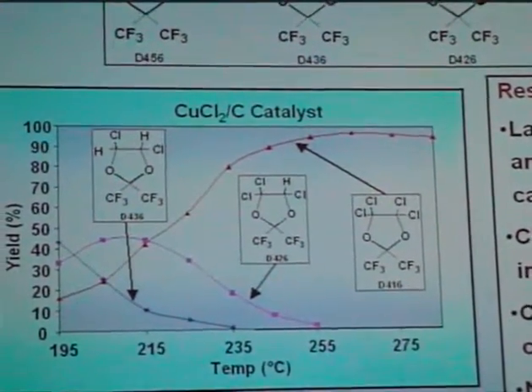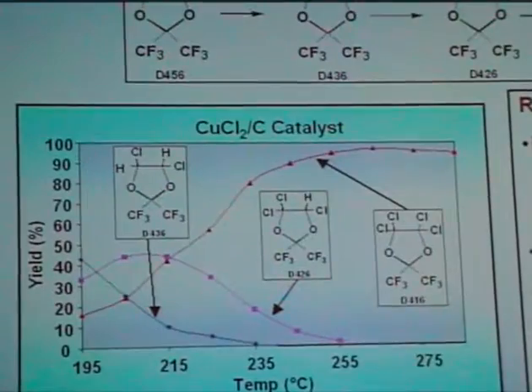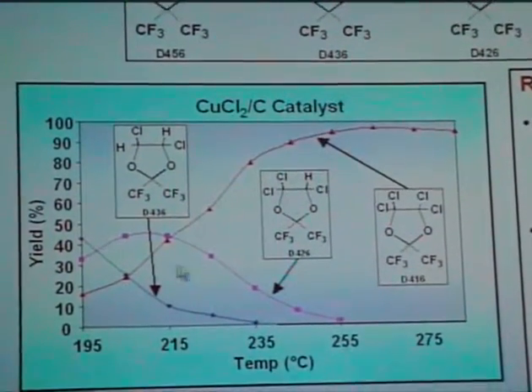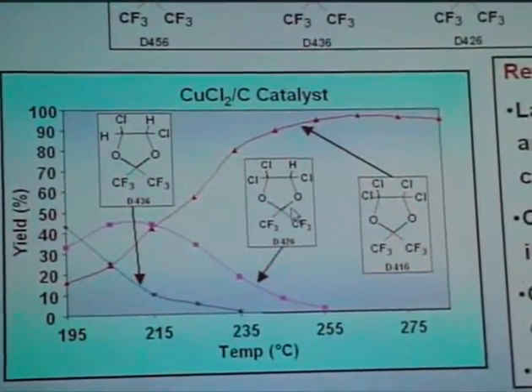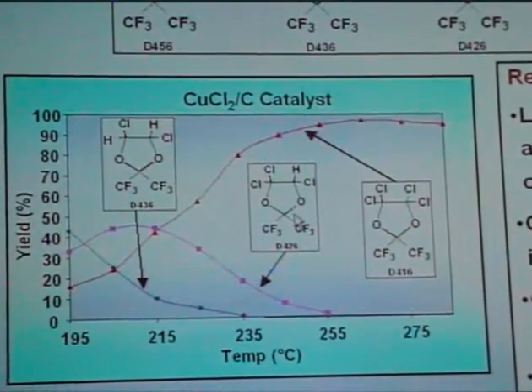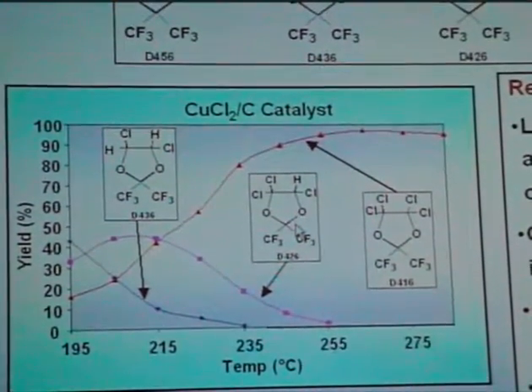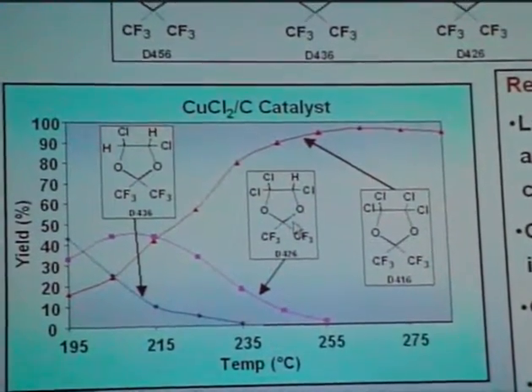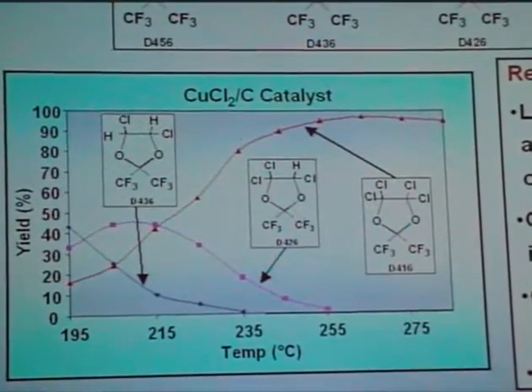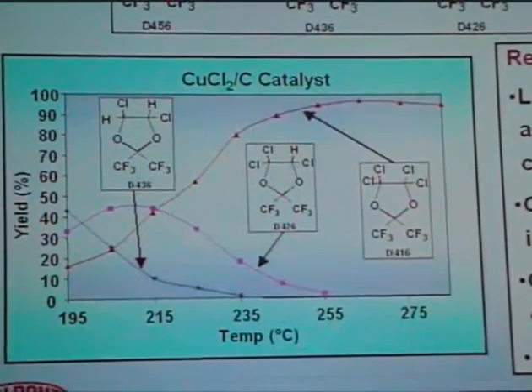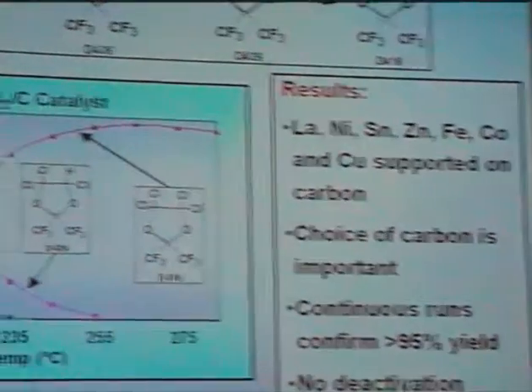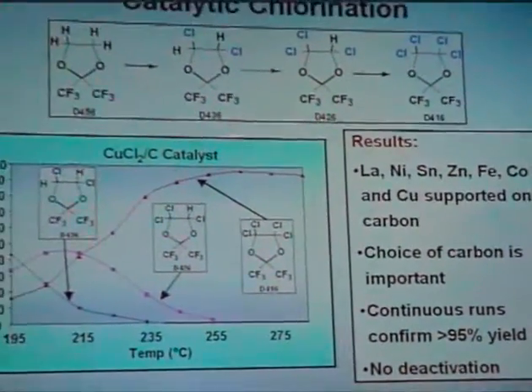By the time you get up to 215 degrees, you can see that we are making primarily the trichloro material, and then going to a little higher temperature, we end up making the tetrachlorinated product in very high yield, well over 95% yield. We have run this reaction, and the catalyst does not deactivate. It's a very smooth chlorination reaction.